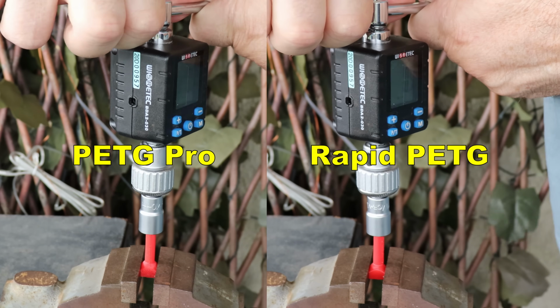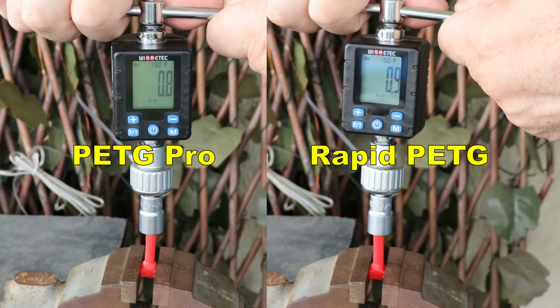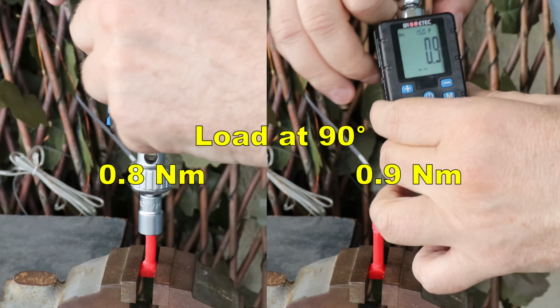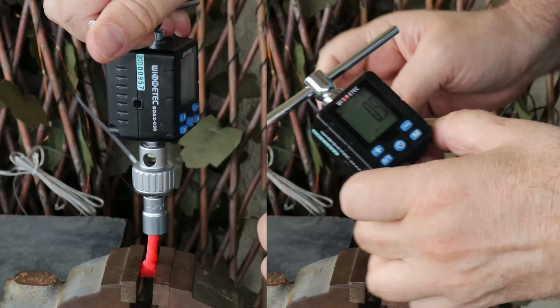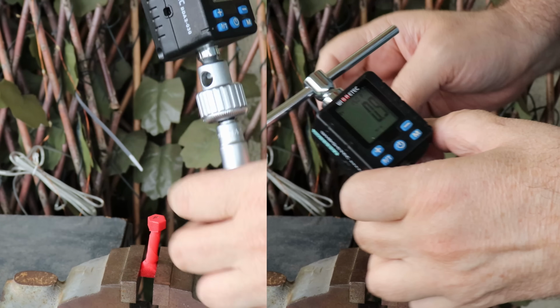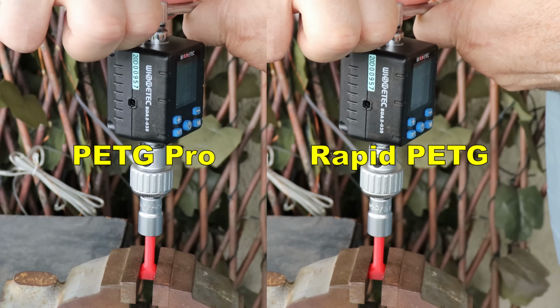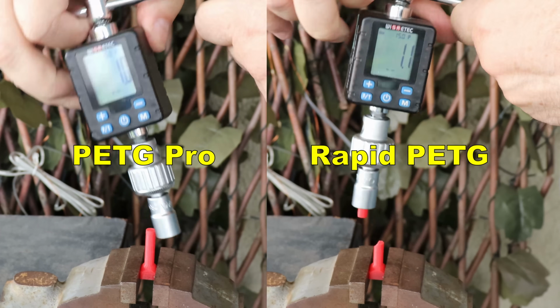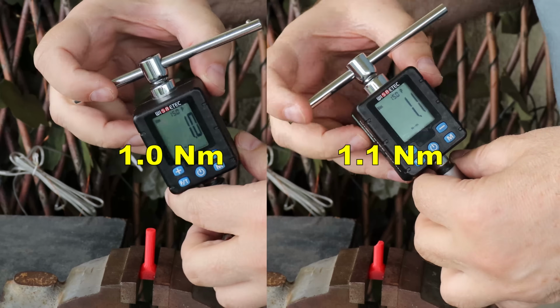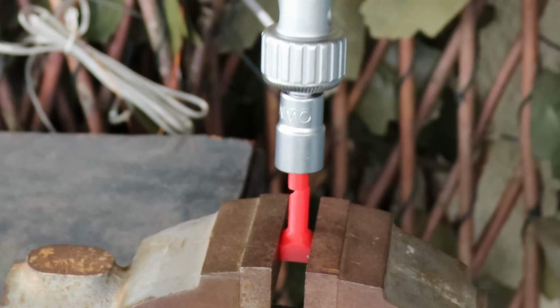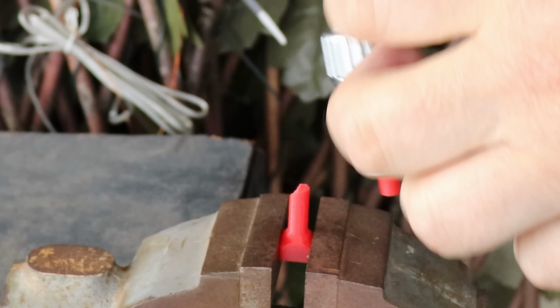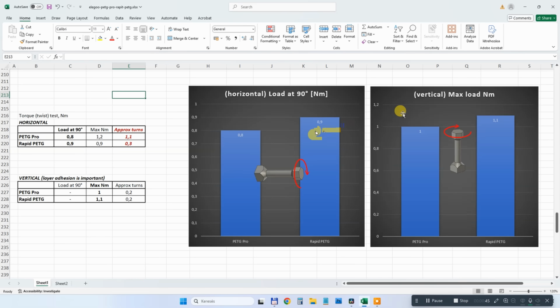Torsion test, side by side two materials. These are printed in horizontal position, loaded 90-degree rotation, and the maximum load 1.2. And these are printed in vertical position, same dimensions. 1. Nice break on rapid PETG, not along the one layer. This is a sign of the good layer adhesion. In both cases the rapid PETG was stronger, but the difference is not big.